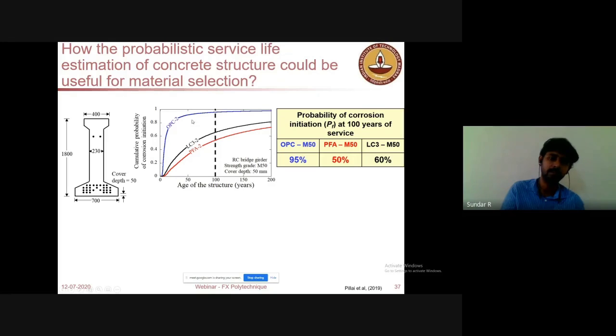So eventually we have to look for other materials. So what are the other materials? We have this ternary blend LC3 and then the binary blend Portland Pozzolana cement. If you look at those two, we could see that there is only a 50% chance of corrosion. So it's quite safe.